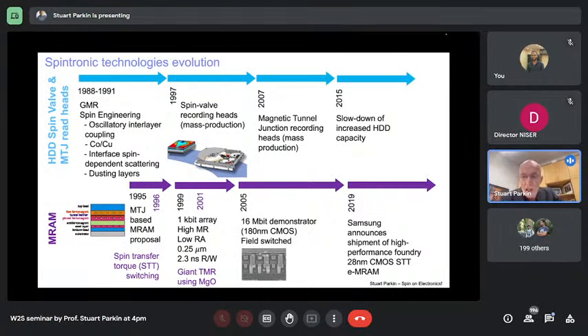Now, we can see for the last several years, the magnetic disk drive technology is evolving very slowly, so slowly that there are only two major companies left that build magnetic disk drives, and both those companies have decreased their research efforts because basically this is a technology that is difficult to evolve beyond its current state. And basically it's limited by the size of these tiny magnetic regions in a magnetic film that can be written and can be detected. They can actually be detected. It's the writing that is the problem today, and the thermal stability of those regions. As you shrink the size of the magnetic regions, the total net magnetic anisotropy becomes smaller, so you need to increase that anisotropy, and that means you need much higher writing fields. And there's a limitation to the size of the writing field that can be achieved in a disk drive.